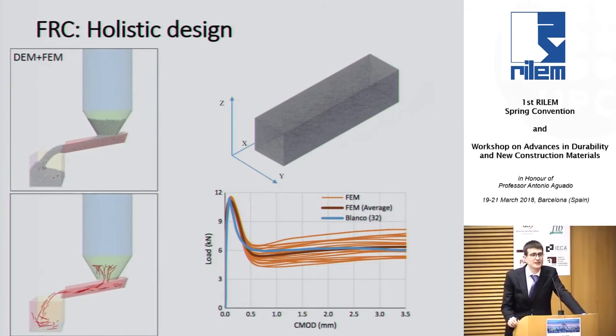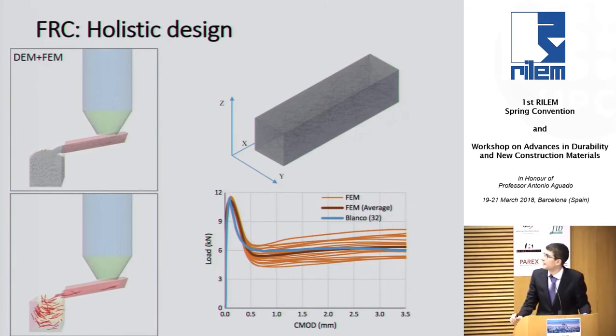We also tried to push a more holistic assessment of fiber distribution using advanced numerical models. In this case, you see here the result of discrete element modeling of the production of a specimen, for instance, in which with small particles, together with the fibers, we try to simulate this flow of concrete and predict how the fibers are going to orientate inside the element. Right? So instead of having to produce elements, we can try to make first predictions with good adjustments using this type of method. And then we can combine this with finite element simulations to predict what will be the mechanical response of the element, simulating fiber by fiber.